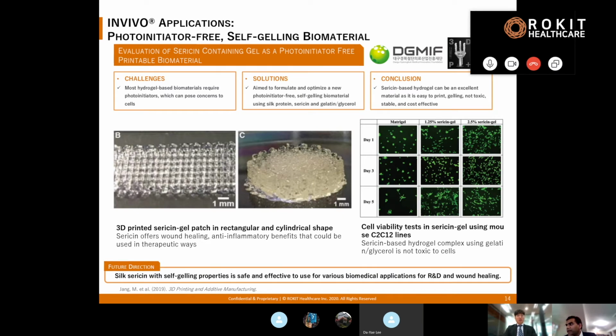So this group combined this new bioink, the sericin protein from the silk, with gelatin and glycerol, and came up with this self-gelling biomaterial. And they were able to confirm that the gel can create high precision scaffolds, as you can see here, with very high resolution of 200 to 500 micron pore structures. And they also assessed the cytotoxicities as seen in this panel. So all of that checks good and promising.